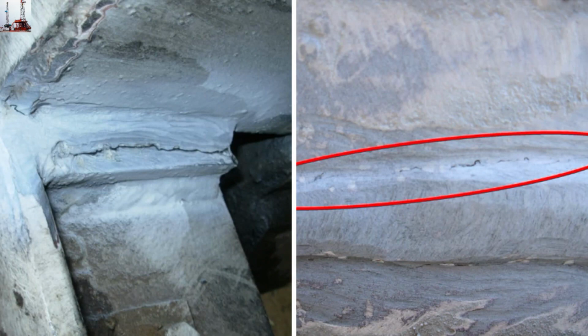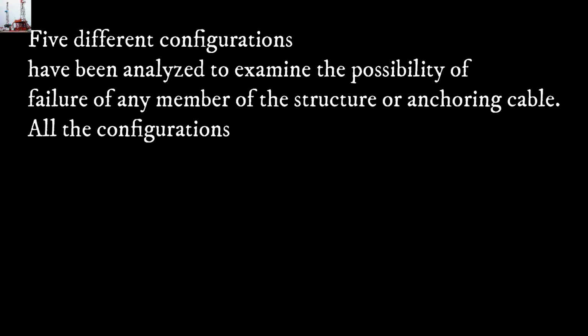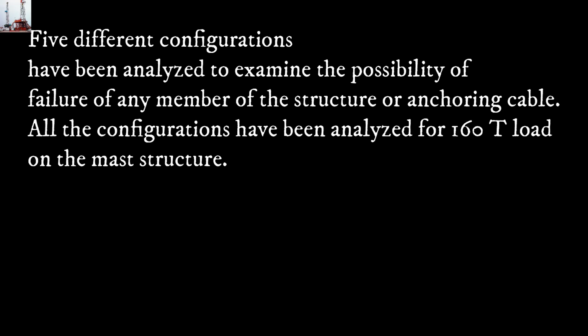Fig. 4. Magnetic particle examination revealed the presence of cracks in the weld joints at many locations of the undamaged part of the mast structure. Five different configurations have been analyzed to examine the possibility of failure of any member of the structure or anchoring cable. All the configurations have been analyzed for a 160-ton load on the mast structure.